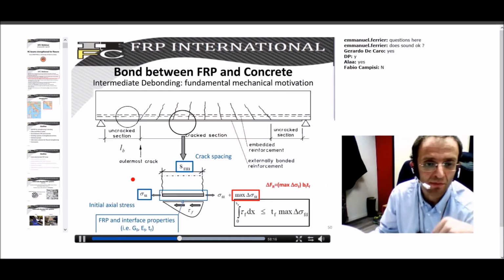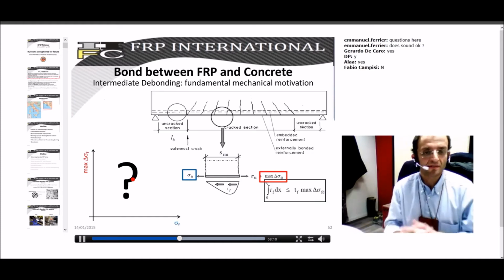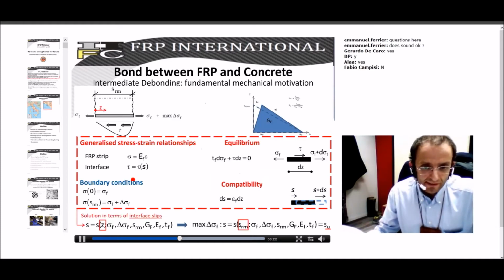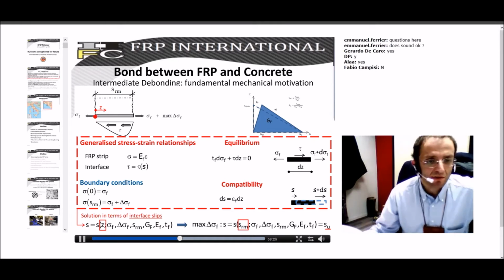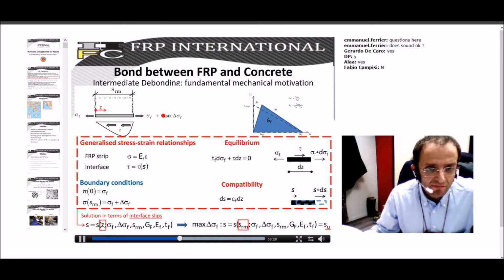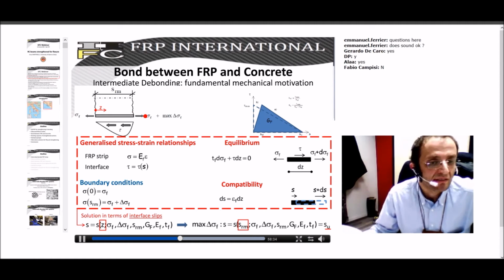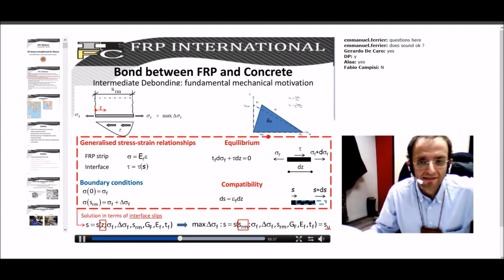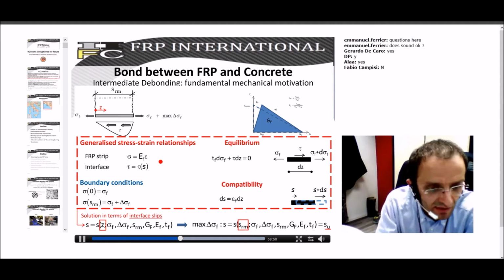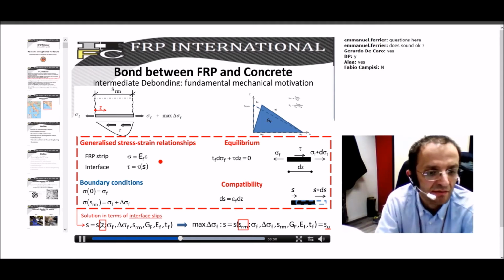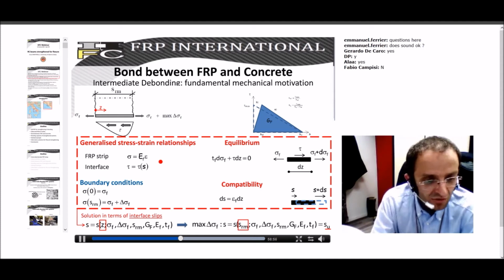In this case, for intermediate debonding, we have two non-zero stresses, and our objective is to evaluate how much is the maximum delta sigma resulting in debonding at the interface, resulting in the fact, for instance, that in this point the maximum slip attains S_u, which is the maximum interface slip before debonding occurs. So basically we can put together all these equations. I omitted all the mathematical details. Of course, if anybody is interested, we can discuss later in the coming days the mathematical details of this problem.